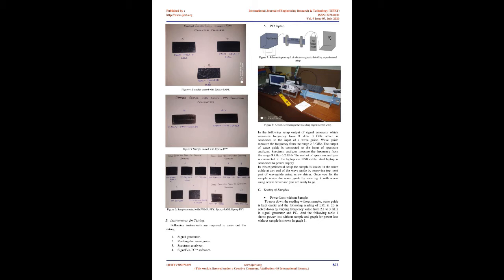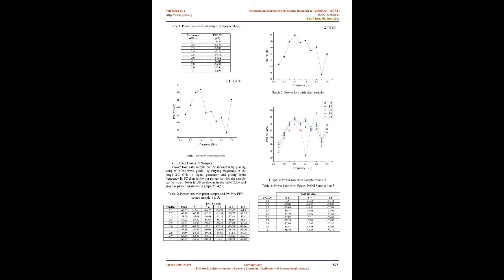3. Experimental. A. Preparation of conductive composites coatings. PMMA. Previously prepared PMMA is weighed in a glass container, to which 1% weight ratio of the conducting polymers is added, with a few drops of castor oil to increase the flexibility in the film. The mixture is thoroughly mixed without forming air bubbles. It is then poured onto acrylic-based material cut into dimensions of 3.4 x 7.3 cm. It is then placed in a desiccator for 24 hours. During this time the solvent slowly evaporates, leaving behind a coating of conductive composite.